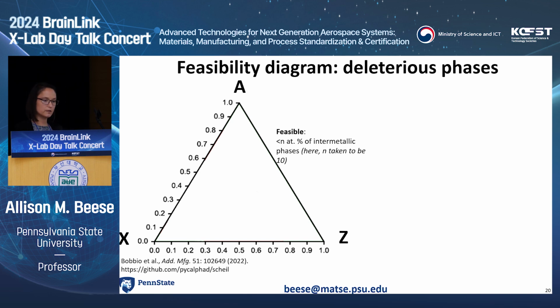So the initial approach that we came up with was this, I'll denote as a feasibility diagram for deleterious phases, where we said, okay, everything that we'd looked at in those previous samples showed that we could predict the phases if we looked at two extremes: equilibrium and then Scheil solidification. So what we're going to look at here is a ternary element space where we could say that a composition is feasible if we have under a certain amount of intermetallic phase. That's a user-defined value, and here we'll take that to be 10 atomic percent.